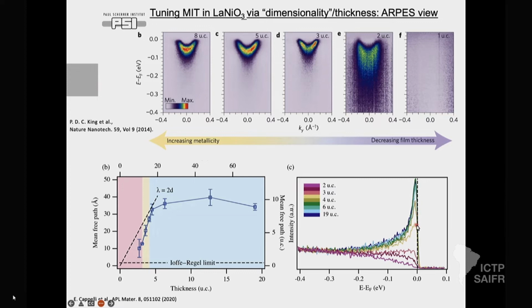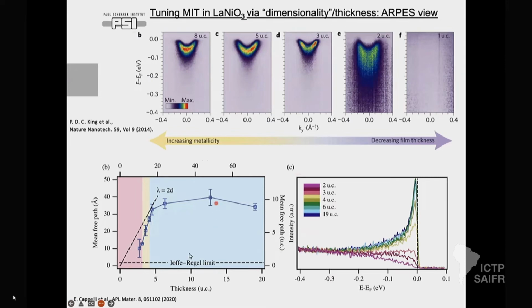So this is what you could see. This is the quasi-particle peak at the kF, somewhere here. You are taking the cut down in energy. So the quasi-particle peak drastically went down when the thickness went down, telling us that there is something happening with the localization. And in order to prove it, the group here did more analysis, looking at the Ioffe-Regel limit, and seeing that actually localization is still above it, even for the insulator. But what really happened is that the mean free path calculated from this spectrum is very much affected below 5 unit cell of the film thickness. So there is some kind of crossover above and below 5 unit cell, which was also seen in previous studies done by others.